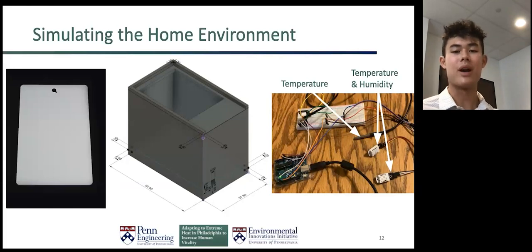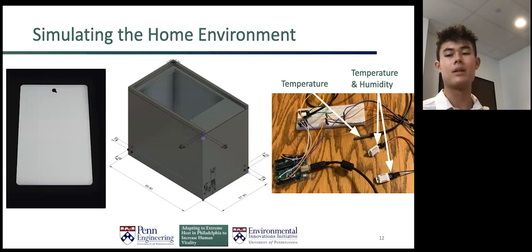And then once I had this apparatus ready, I used an Arduino microcontroller to program 3 different temperature sensors that I use to monitor the box. So the top temperature sensor, which is the metal probe, attaches directly to the metal substrate to measure its temperature. And then the 2 white temperature and humidity sensors go inside the box at the bottom and outside the box. So I can contrast the air temperature inside the enclosure with the air temperature outside, the ambient conditions.